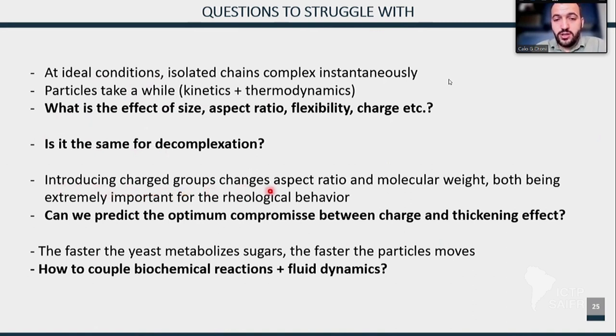Also, introducing these charged groups in the particles changes a lot the aspect ratio and the molecular weight. So it's not only beautiful, there are side effects, there are drawbacks, right? Both being extremely important for the rheological behavior. So can we predict an optimum compromise between charge, thickening effect and rheological behavior to stabilize, for instance, multi-phase systems? And finally, the faster the yeast metabolizes sugars, the faster it produces CO2 and the faster it moves upwards, right? So how to couple these biochemical reactions to the fluid dynamics so we have enough subsidence to induce an optimum reaction, sugar consumption, and movement in the vertical axis, which might be interesting for mass transport.